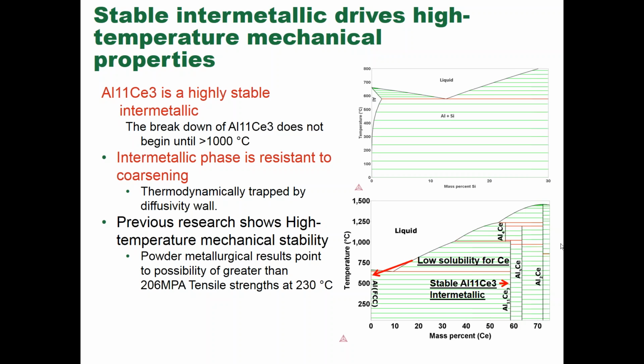When you mix aluminum and cerium, you get a highly stable intermetallic, Al11Ce3. The breakdown of that intermetallic does not begin till about 1,000 degrees C. So it's very, very stable at high temperature. The intermetallic phase is resistant to coarsening.